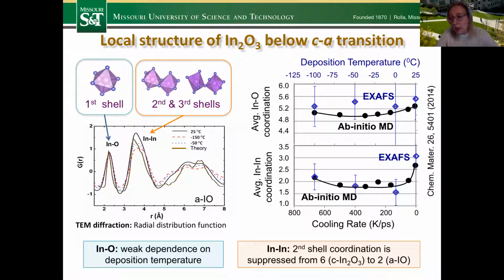Well, we use the experimental EXAFS measurements and then got the information from our theoretical modeling on the distances in the first, second and third shells, and also the coordination. And we compared the scale in the experimental deposition temperature to the theoretical scale in cooling rates, and we got quite a good agreement. Again, for the structure here, I'm showing only the coordinations, but we also did the distances and the distortion factor. So we are comparing really well, and that gives us hope that now we can understand that mobility peak based just on the different cooling rates in indium oxide.